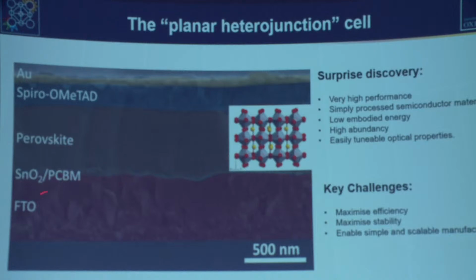We've got a conductive oxide. We've got a thin electron selective layer - you can barely see it in this electron microscopy image, it's very thin, just a few tens of nanometers in thickness. We've then got the perovskite absorber, then a p-type layer, and then a metal top contact.